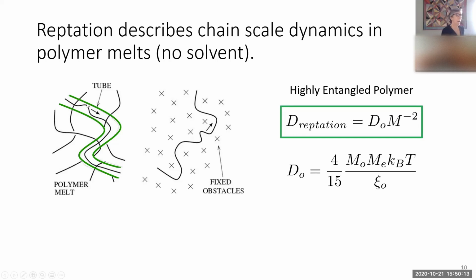Okay. So this is a schematic trying to illustrate the entanglements, or you can just call them X's, and realize that the polymer here on the black line can't move through one of these X's because these are the entanglements. Okay, so we understand that the reptation goes as this prefactor times the molecular weight to the -2, and this prefactor has the friction coefficient, the temperature, and this molecular weight entanglement. Okay, so that's what we know. And this was well established theoretically and experimentally in the 80s.